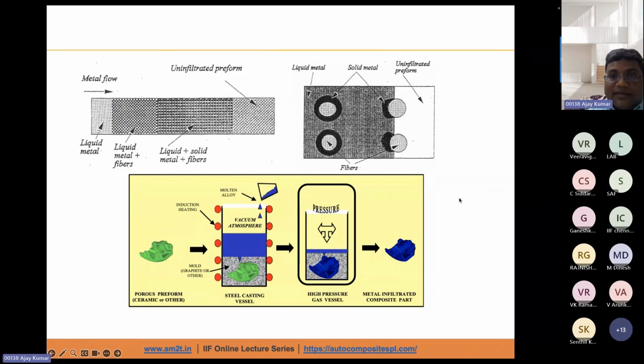When we talk about the pressure infiltration, you can see here we have the preform material, and then we have the liquid metal. We can make the preform, and from here the particles can infiltrate through the liquid metal. So we have the liquid metal here, then we have the solid metal, and the uninfiltrated preform. This is how this process helps, and the particles will infiltrate through the liquid metal, and we will get a fine distribution of the second phase particles in the metal matrix.